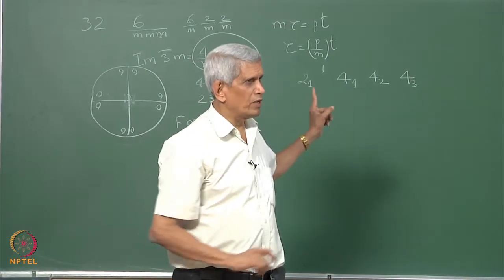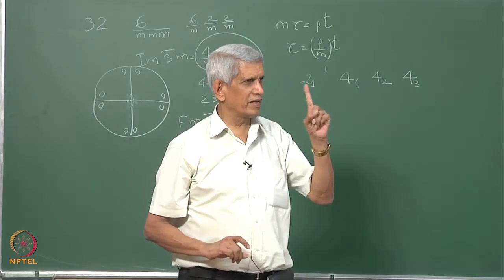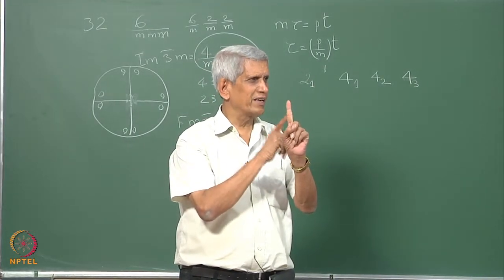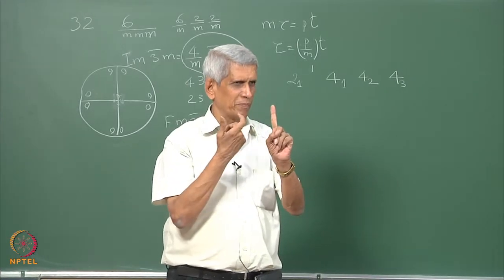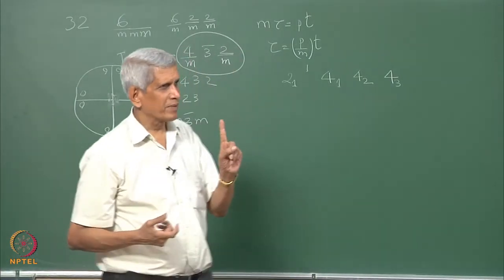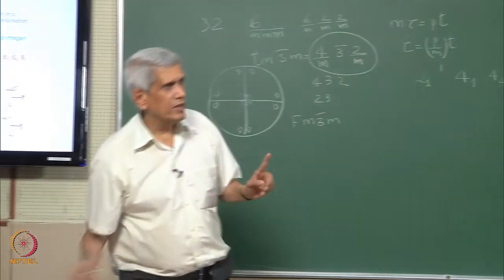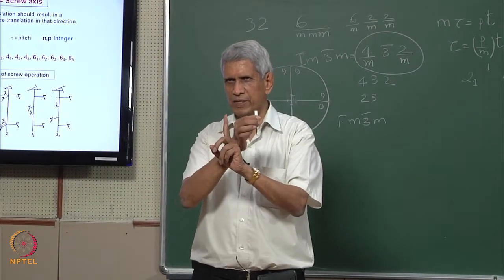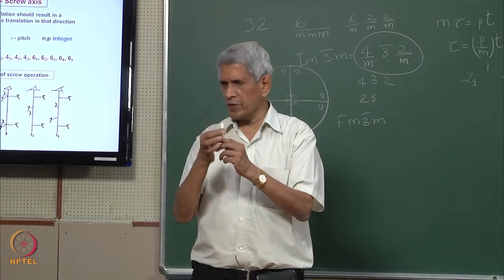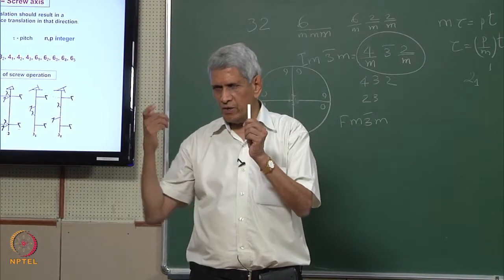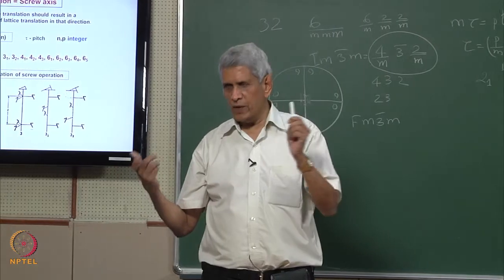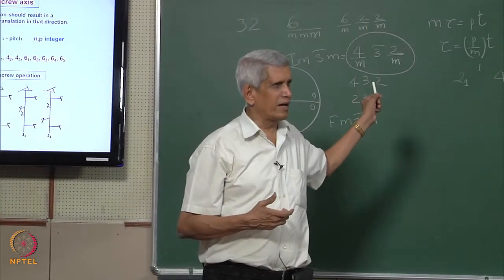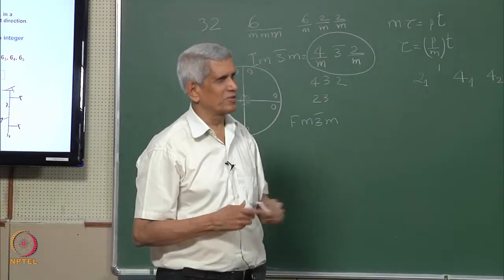But why we are writing it in this way is that we are following one convention of taking the sense of rotation. Because here the way we considered is, in one case the sense of rotation is clockwise and another is anti-clockwise. If we take the sense of rotation in the same way, we will notice that the pitch is not going to be 1/4, it is going to be 3/4.